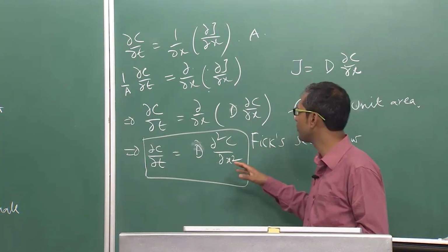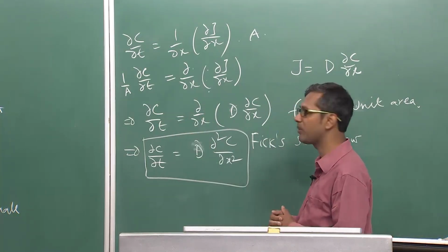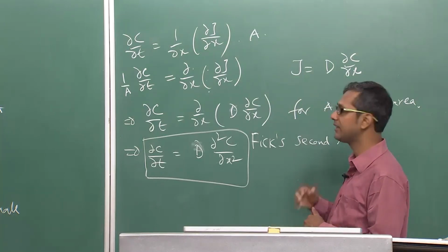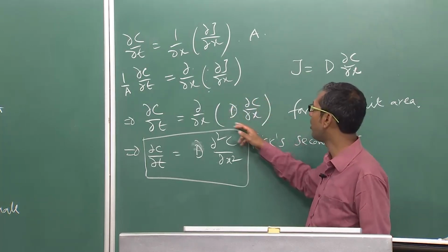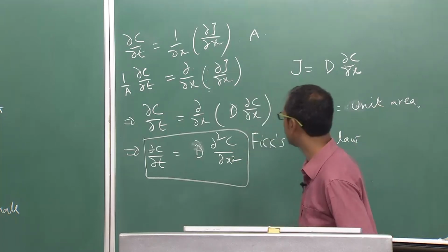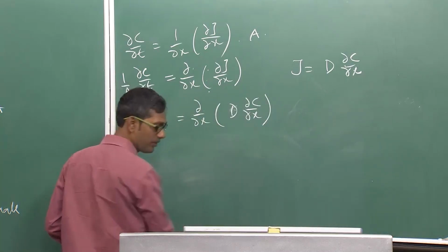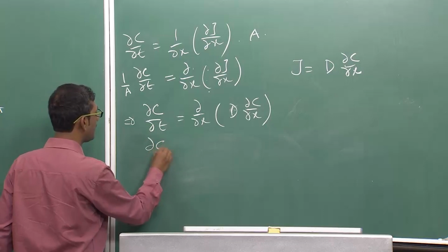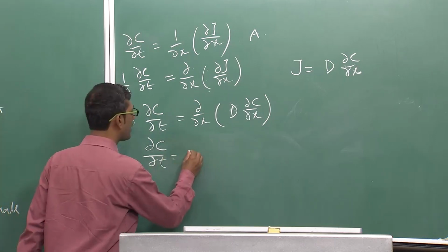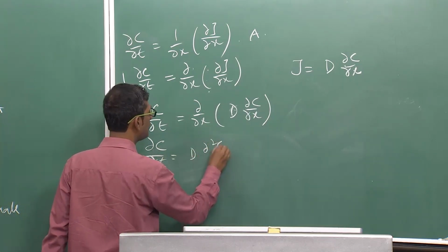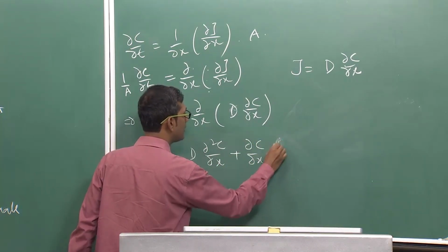So, if you really want to solve this problem, which is the fundamental equation required to solve all kinds of diffusion problems in the literature, in different industrial or academic problems, we need not take this D out, rather we should do a little more maths and try to find out how to solve these problems in a different way. If I assume D is not completely independent of spatial variables, we can expand this equation. So, this will be this plus del C by del x multiplied by del D by del x.